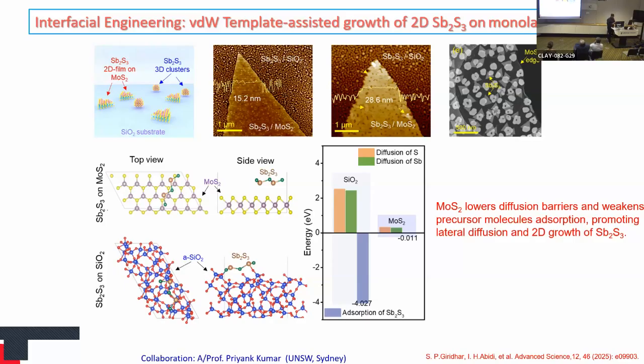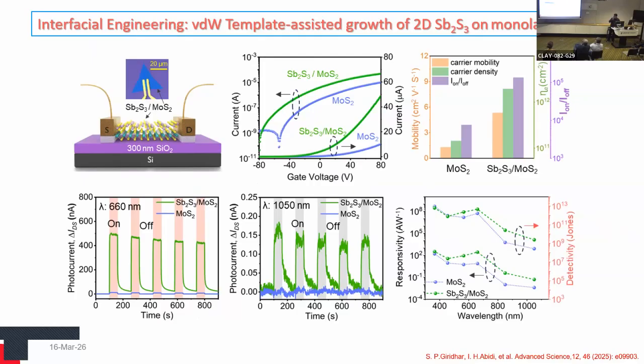So this is not just Sb2S3. You can also grow other 2D materials on top of it using the same phenomenon of this van der Waals template assisted growth. So with the heterostructure, once we tested these heterostructures, the most important thing it enhanced is the broadband optoelectronic detection. For example, MoS2 itself is only active until 660 nanometers in the visible range. But once we have a heterostructure with Sb2S3, it also responds to higher wavelengths into the near IR and IR, up to 1050 nanometers.